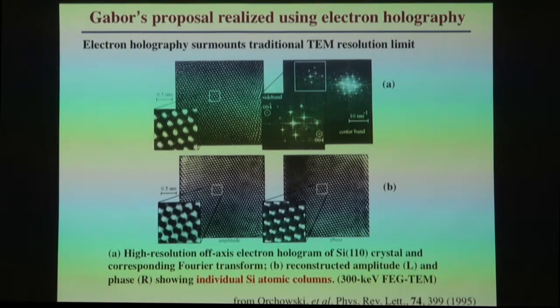In the parallel work of Hannes Lichte and colleagues and students, Orchowski et al., they were able to use electron holography to overcome the traditional resolution limits. So here is the original hologram, and an enlargement. You take a Fourier transform, you get the autocorrelation function in the center and the sideband here, shown enlarged, with 004 spots showing up in this case. You then do an inverse Fourier transform on the sidebands, and you finish up with either the amplitude or the phase.